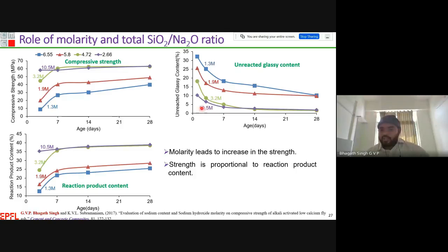But in the case of 10.5 molars, almost 40% of the fly ash already dissolved between 0 to 24 hours. But in the case of 3.2 molars, only 20% of the glass is dissolved. But after 7 days, you can see the unreacted glassy content is the same for both 3.2 molars and 10.5 molars. And if you observe the reaction product content from 7 days, there is no much difference in the reaction product content. It indicates that 3.2 molars is more than sufficient to dissolve the glass present in fly ash. If the fly ash glassy content is less than 60%, then there is no point in using 10.5 molars or higher molarity as the literature says.